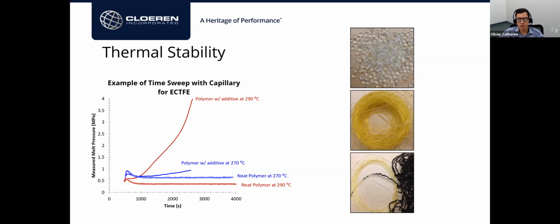And so for good extrusion, we don't want to even be there. So whenever you see shear stresses that are higher than the critical shear stress, yes, the model can be wrong if you don't take into account any slippage, but that's not an area you want to be in the first place. So you really want to be in that Newtonian flow and trying to understand if the shear stress values are really below that critical shear stress. That was the goal there.